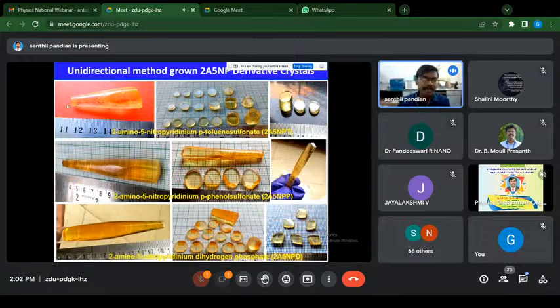Here what we have done is we have mounted a seed crystal at the bottom of the glass ampoule, and we have poured the saturated solution inside the glass ampoule, and we optimize the temperature at the top and bottom portion. So when the solvent evaporates, the remaining solid particles are growing as a single crystals, and we can able to grow this much of large single crystals by this unidirectional method. These are the as grown 2-amino-5-nitropyridinium derivative single crystal, and these are the cut and polished wafers.